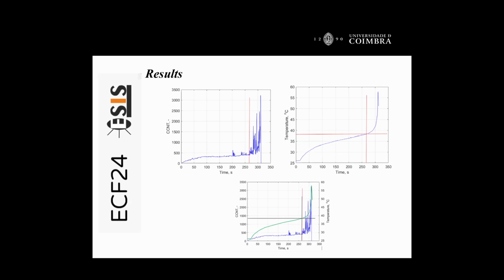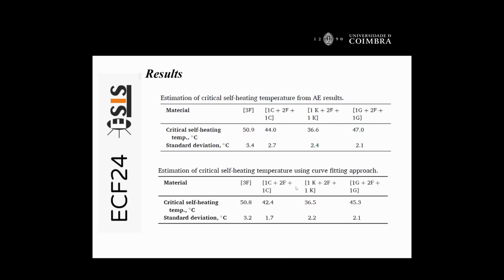Okay, in this case, this is the graphic that we obtained. In the right position, we have the graphic of temperature versus time, obtained in the previous results by thermography. And when we combine these two graphics, we can observe that the results coincide very well with each other. We obtain two lines, the critical self-heating temperature value, and these lines are very well superimposed between the strategy obtained by thermography and the strategy used by acoustic emission. In this case, we have good results that are proven in these tables.